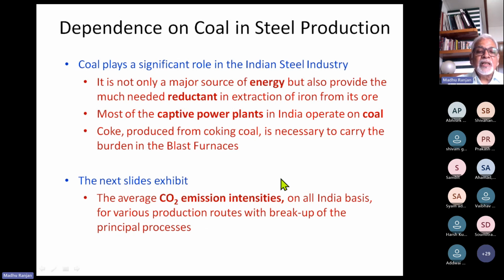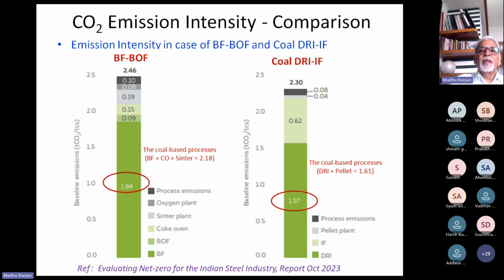So now we see in the next couple of slides the average carbon dioxide emission intensities on all India basis for various production routes with breakup of the principal processes. We have a comparison here between the blast furnace in combination with basic oxygen furnace route and coal-based DRI in combination with induction furnace. We can find that the emission intensity of the blast furnace BOF route is high at 2.46, but the coal DRI and IF has a lower total emission rate, 2.30.